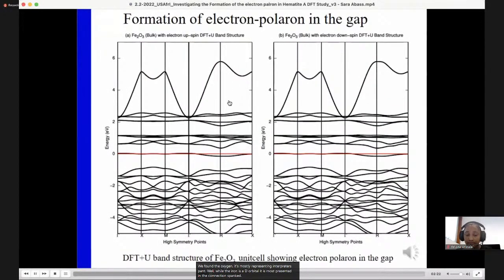And when we introduce an electron into the system of this hematite material, we calculate the band structure again. In this case, we use the unit cell of the hematite structure and show a Fermi level in the gap in both the up spin and down spin band structure. We are able to see a single band, the state of an electron polaron, in the gap. In this system, we also observe the phenomenon that leads to the formation of an electron polaron.